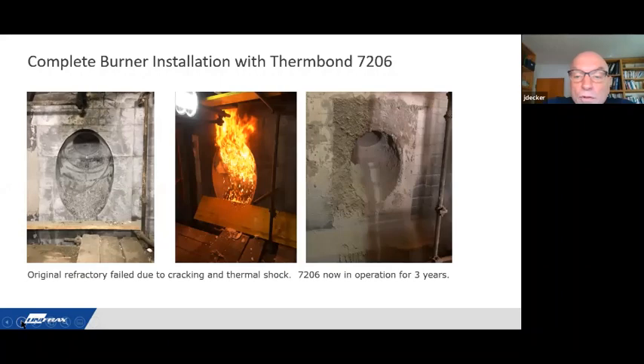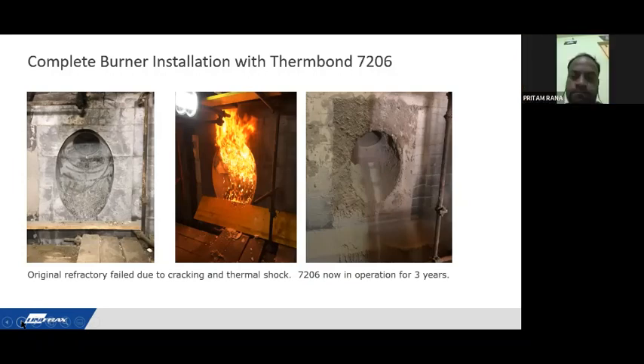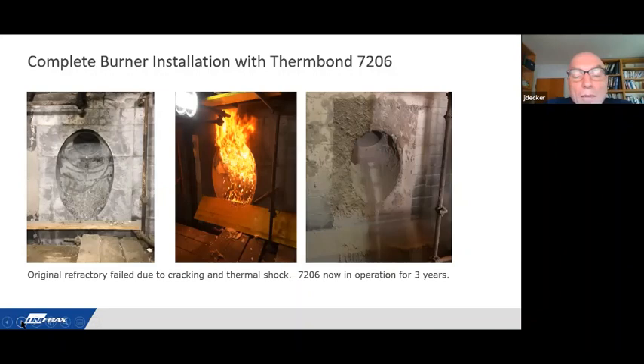This was also one of our first installations. It was a utility burner, also in a power plant, roughly 3 tons involved. They had a polystyrol foam core installed, and they just ignited it. I was actually shocked when I saw it, but then I was impressed with the thermal shock resistance of this material. It was a kind of proof that we did our homework, and it really works in the field. On the very right, you see the same burner after 3 years in operation, and I think it still looks very good. So again, no compromise on performance, although we have all the advantages of fast firing material.